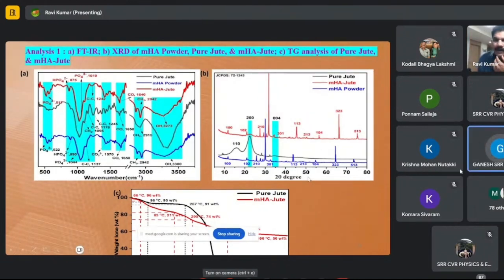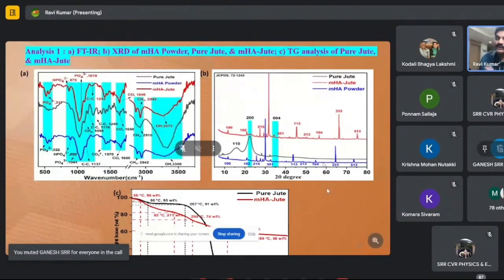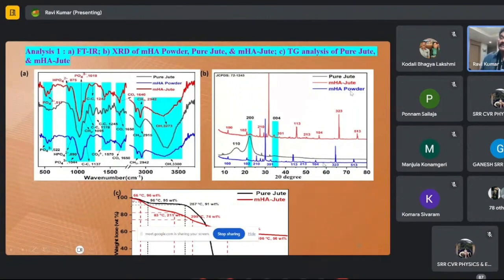Next, we go to the crystallinity of the material. The crystallography is shown by XRD, and the 2 theta degrees show the crystallinity very strongly because MHA is already a crystalline material. You can observe the pure MHA powder, which is the blue one, and it is very crystalline. After deposition of MHA on the jute, it also shows very crystalline, that is the red signal. The black one is pure jute. Pure jute doesn't have any crystallinity, and the peaks are also not very good.